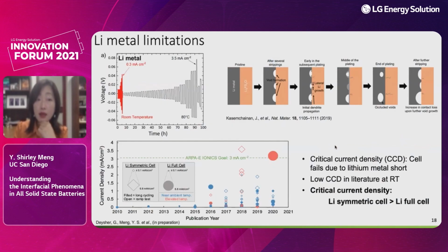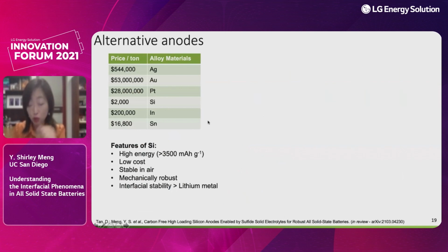So the lithium metal limitations have been very well summarized in this slide. When we run to high critical current density, we can run into void generation. And when we go to higher temperature, we can actually promote side reactions between the cathode and the electrolyte. So what should we do with the anode strategy?